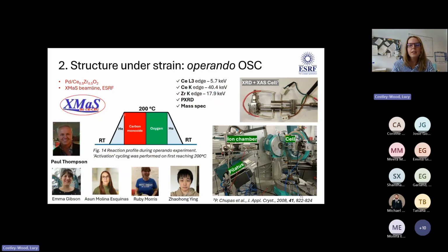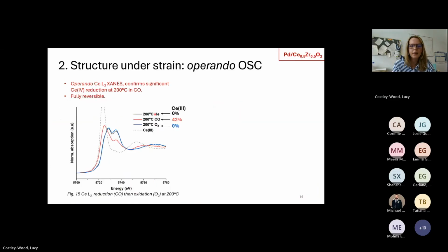We increased the temperature. We cycled between the two states, the reducing and oxidizing state, a while first to clean the surface and get the material moving. And then we left it under carbon monoxide and then left it under oxygen. So looking first at the cerium L3 edge, this is a more popular edge to measure. It's very XANES-sensitive, but you can't get the EXAFS. So we were using it just to confirm that the reduction was in fact happening. And we can see that at 200 degrees, when we switch to CO, we have 42% cerium 3. And then when we oxidize the sample again, we go back to 100% cerium 4. So this is a reversible process.